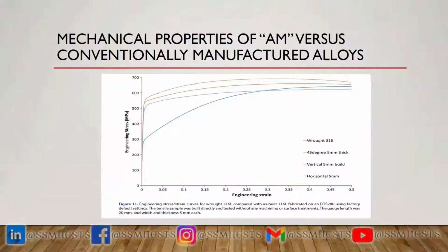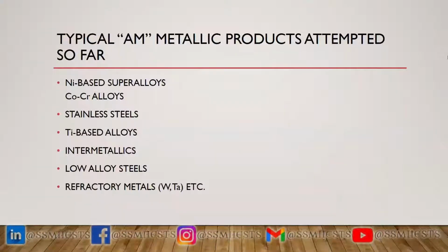And if you look at the property, the bottom one is for the wrought material. It's a wrought, I think, stainless steel, doesn't matter. The upper ones are all made by the AM process. You can see higher strength and very good elongation also. Next one, please. Yeah, so typically, these AM metallic products have been attempted till now: nickel-based superalloys, cobalt chromium alloys, stainless steels, titanium-based alloys, intermetallics, low alloy steels, refractory metals, etc. The next one, please.